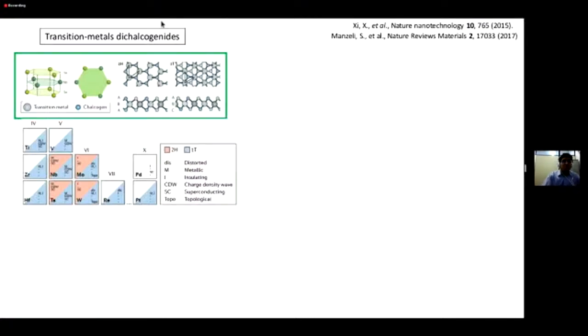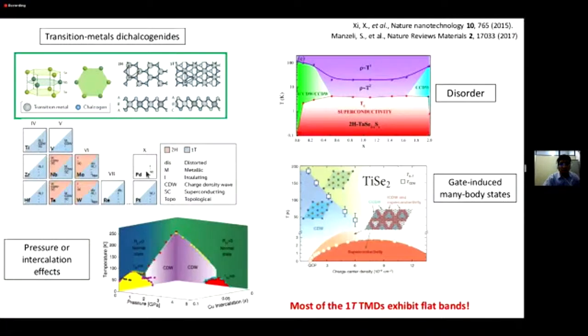Okay, so discussing more about transition metal chalcogenides, it's quite interesting that this kind of compounds present very rich phase diagrams concerning the CDW phase. For instance, here is one example of this kind of phase diagram in which we see the formation of this charge order phase, and that is destroyed when we apply pressure or copper intercalation, and there is the formation of this superconducting dome here, very, very similar to the cuprates.